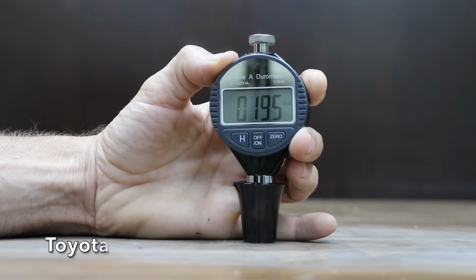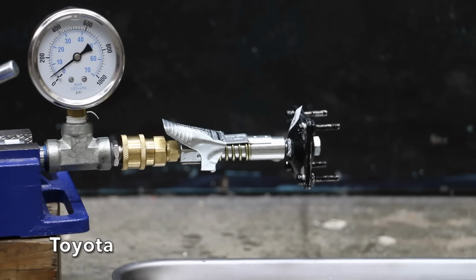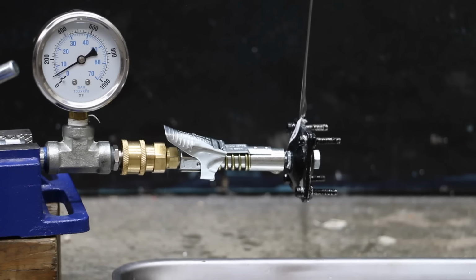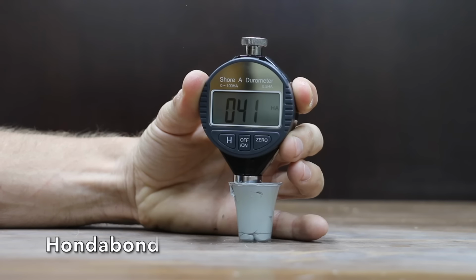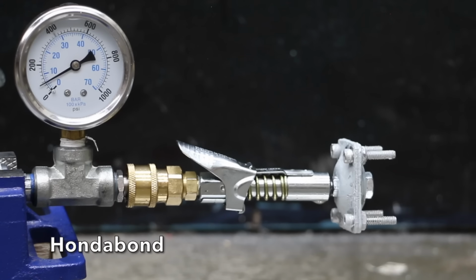And the Toyota is pretty soft at 19.5 and has very good tensile strength at 72.3 pounds. And the Toyota made it to 640 PSI before experiencing a massive blowout. And the Hondabond has very good tensile strength at 93 pounds, but it's also very hard at 41. And the Hondabond began losing pressure at 380 PSI.